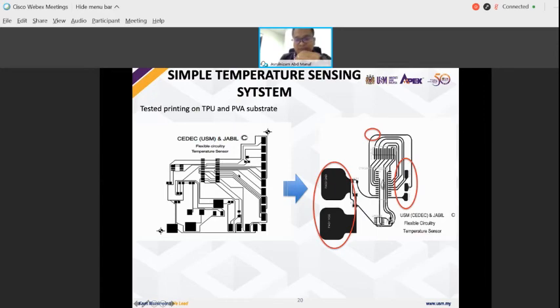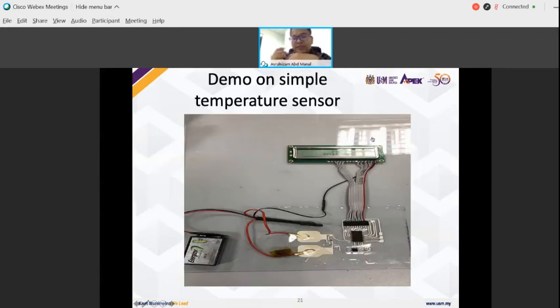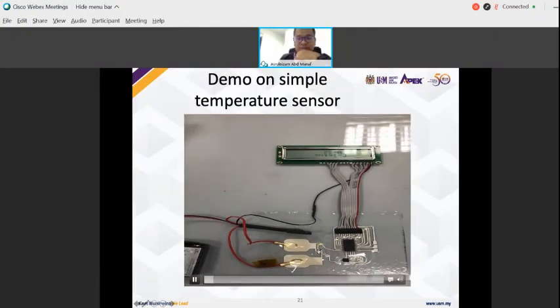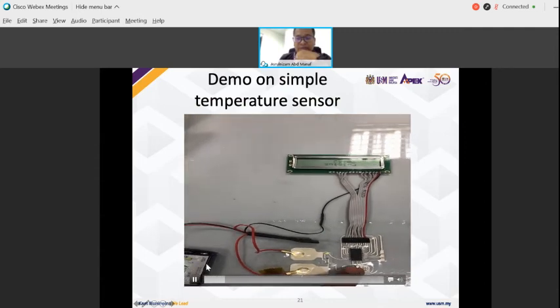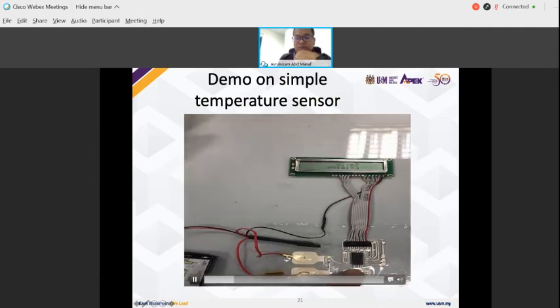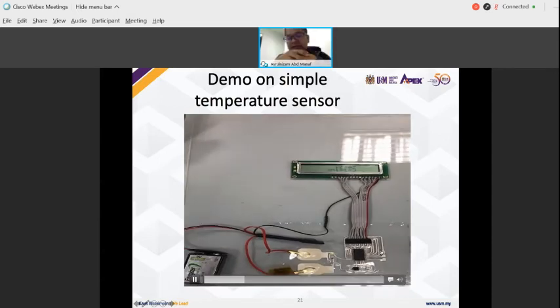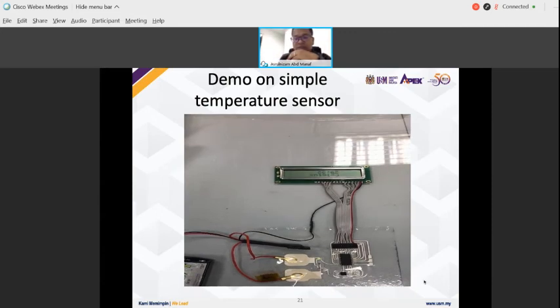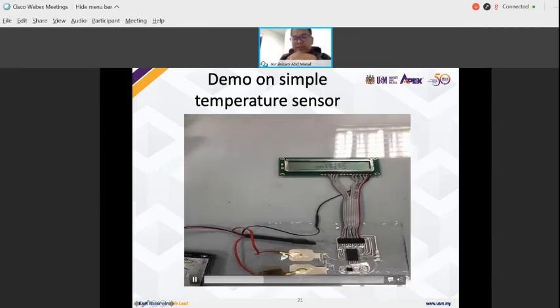This is one of our tests. This is a normal circuit. And this is what we do, printing a flexible circuit, so that we can do some tests on the printable, I mean on how good the printed circuit is. That means how good the ink can be applied as a circuit trace. So this is one of the examples. We check the temperature sensor, just to prove that it is sufficient to drive the current. We need to turn on the MCU, and then control the temperature reading.